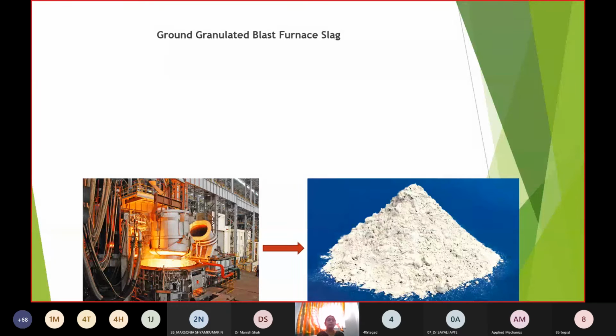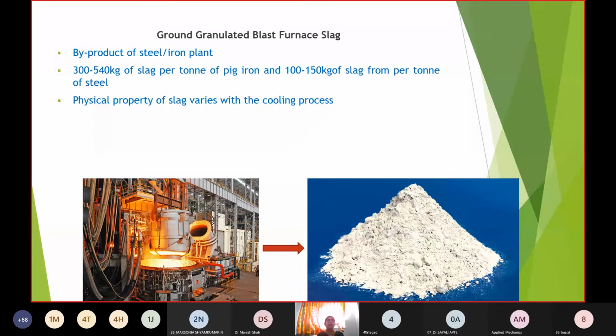And for every ton of pig iron that is processed, I get around 300 to 540 kg of slag, and for every ton of steel that is being produced, 100 to 150 kg of slag is being produced. So the volume again is tremendous and available in huge quantities, and is just being disposed of as it is. After the quenching of the molten slag, granules of the slag are created, which are ground or processed further to make this fine powder as you see in the picture. And the physical property varies with the cooling process, as I was mentioning. Gradual cooling would result in a crystalline form of slag, and glassy and amorphous slag is created due to quick or rapid cooling of the molten slag.